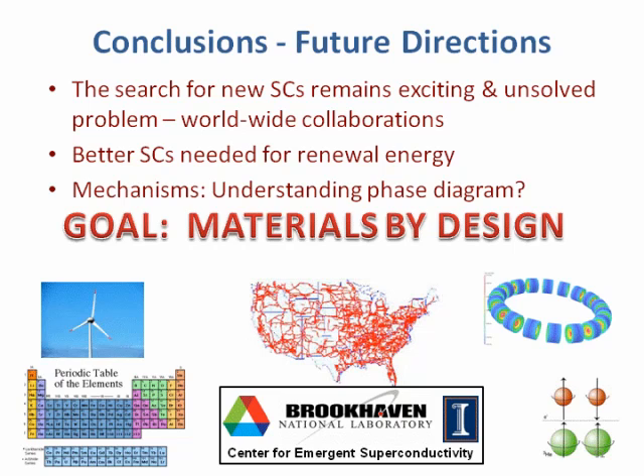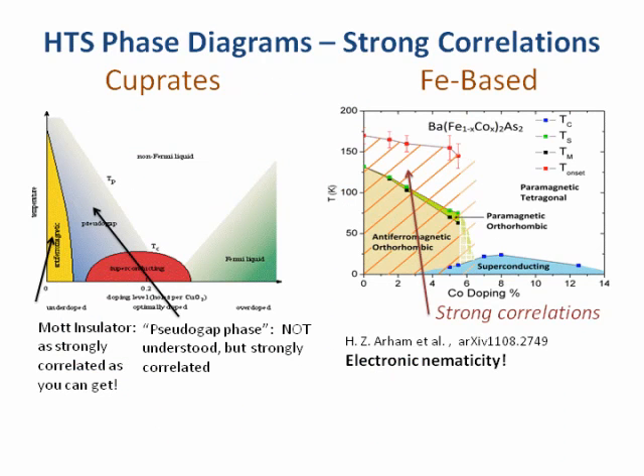So it turns out that this is the material yttrium-bearing copper oxide. That's the cool-grade one. If you make yttrium-1, barium-2, copper-3, oxygen-6, that's what you have here. So we have 1, 2, 3, yttrium-bearing copper. This is oxygen-6, and this is oxygen-7. So you're doping with oxygen. As you put oxygen in there, you start creating carriers, and in these materials it starts superconducting at about oxygen 6.4. If you keep doping even more, oxygen 7.2, 7.5, then you start getting into this area which we call a conventional metal or Fermi liquid.